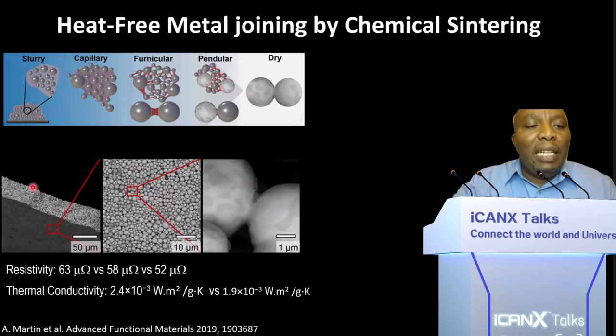And when you do that on a powder bed, this is what you get. You get a thin film of metal that actually retains its spherical structure, but if you zoom in, you can see the neck connections, and it's very conductive. The resistivity of that material is about 63 microohms, and if we use mechanical force, it's about 58 microohms, and the bulk metal has a resistivity of 52 microohms, and the same thing for thermal conductivity.